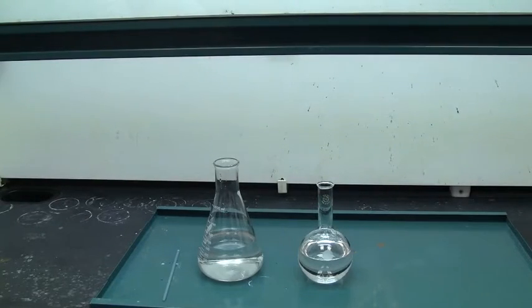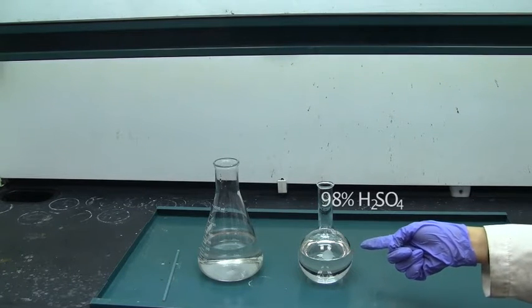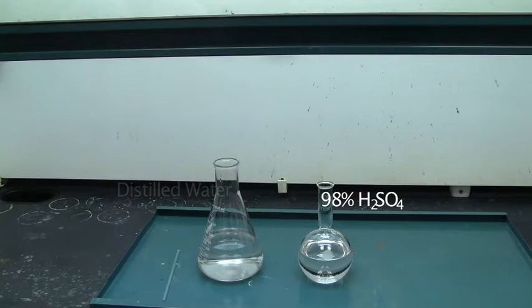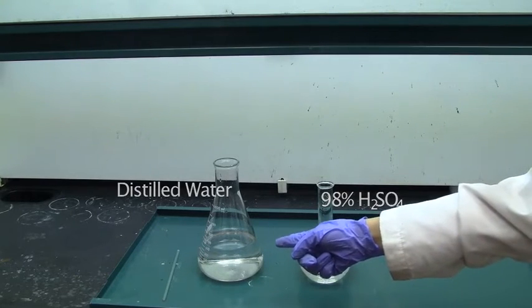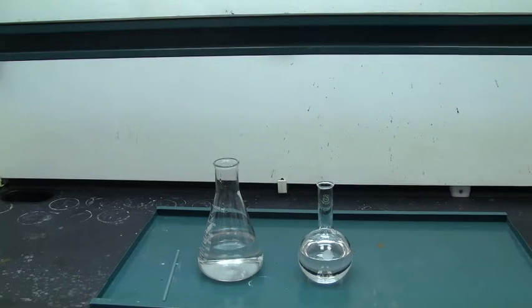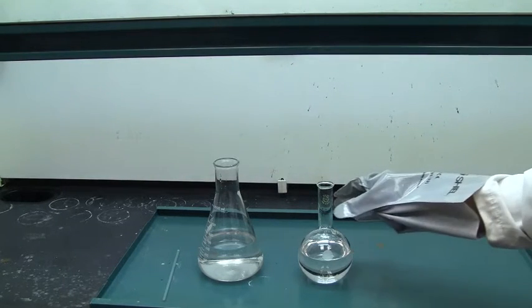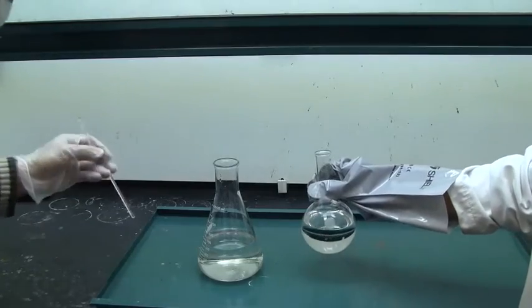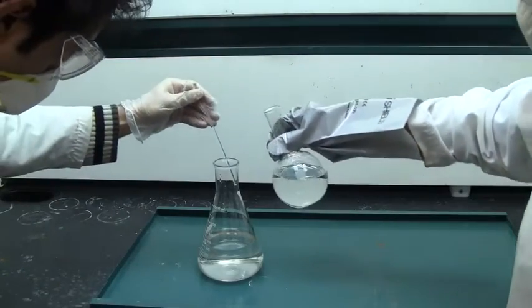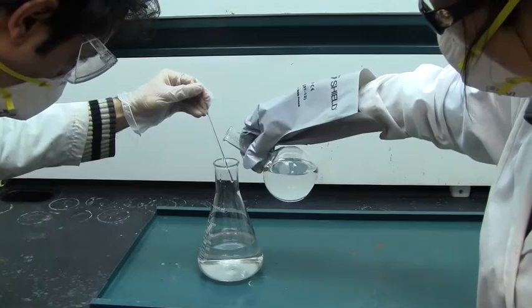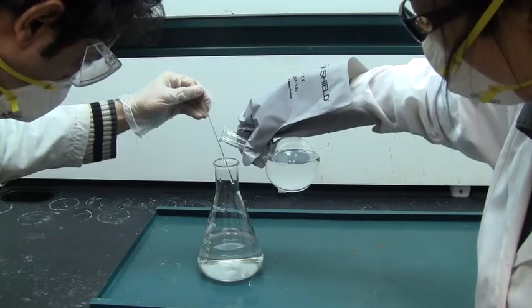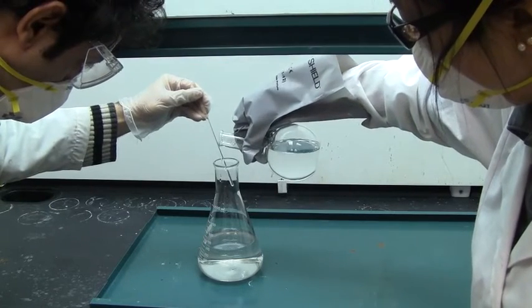In this experiment, we are going to dilute 98% concentrated sulfuric acid liquid with distilled water to obtain sulfuric acid with a concentration of 6 molar. This will be used as the leaching solution. To obtain the 1,000 milliliters of 6 molar sulfuric acid, 325 milliliters of 98% sulfuric acid and 675 milliliters of distilled water are required. Pour 300 milliliters of distilled water in the flask.